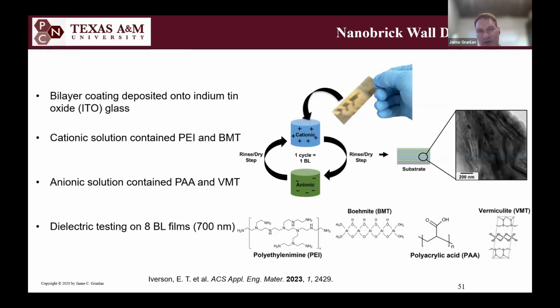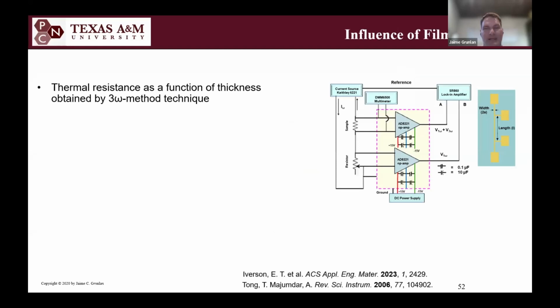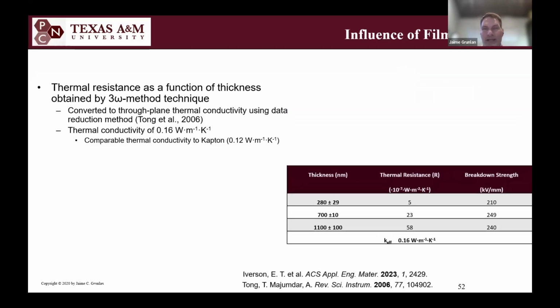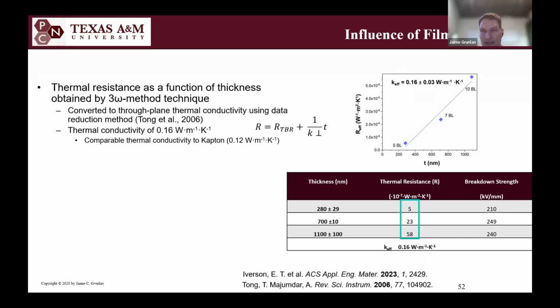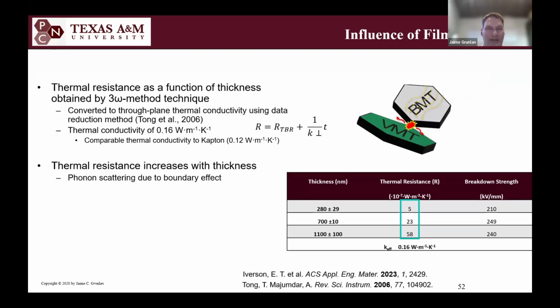And then we made 700 nanometer thick films that were 8 bilayers of the boehmite and vermiculite, stabilized by the PEI and PAA. And so we measured thermal conductivity by doing thermal resistance with another group, Patrick Shamberger's group in the Material Science and Engineering Department. And we measured that these films had 0.16 watt per meter Kelvin, which is not great, but at least it's similar to Kapton. So it's not terrible. It turns out PEI, PAA by itself is 0.5 watt per meter Kelvin, which is pretty high for just a pure polymer, not crystalline.